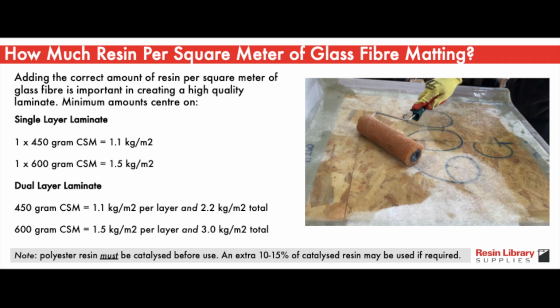If you're building something that requires a bit more durability, like a walkway or a balcony, then adding 2 layers of laminate is a good idea. So if you're doing 2 layers of 450 gram matting, then add 1.1 kilogram per square meter per layer and 2.2 kilograms per square meter in total.